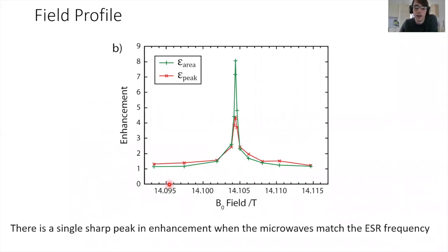Okay, this is now, if we have a constant frequency of microwave irradiation and we sweep the field, we get no real effect until we hit the electron resonant frequency. So when our microwaves match the resonant frequency of our electrons, that's when we get saturation of the transition. We start to equilibrate these populations, and then they can cross-relax and hyperpolarize nuclei, and we measure that as an enhancement. And this is a pretty sharply peaked effect. Again, for those unfamiliar with DNP, this differs from the solid effect and the cross effect, where you see multiple features. A characteristic of the Overhauser effect is that we see just a single feature at the electron resonant frequency.